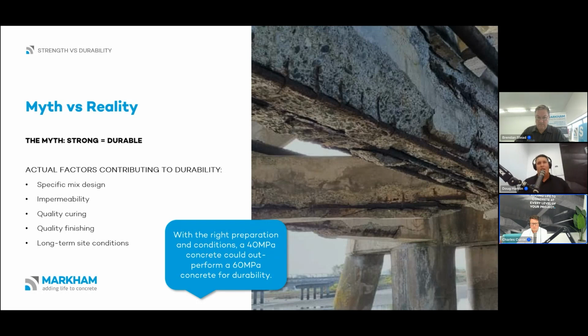So you could have a 60 MPa concrete that gets poured on a bad weather day. You're resulting in a whole lot of drying shrinkage or plastic shrinkage cracking, and that structure is much more susceptible to corrosion damage and deterioration than, say, a lower MPa concrete that's poured with the right conditions, right admixtures, everything's been thought out, and it's a quality concrete that you end up with.